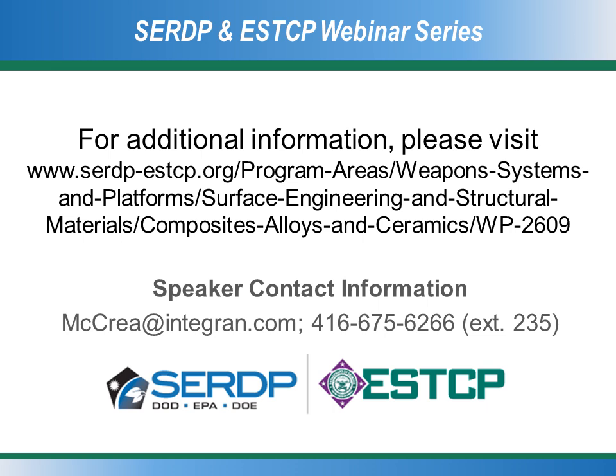Can you please comment on the salt spray requirements and performance of nanostructured coatings versus hard chrome? Yep. In the slide that I previously showed, due to the fully dense microstructure and no micro cracks, you do see significant improvement in the time to red rust versus electrolytic hard chrome coatings directly deposited onto steel.